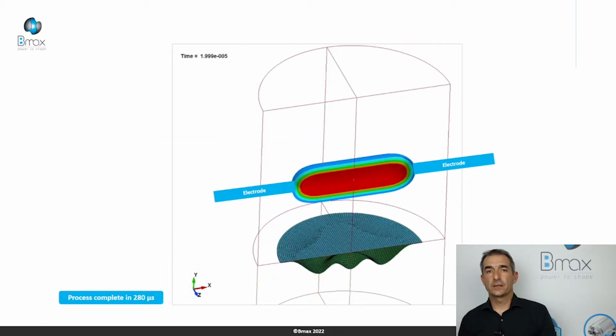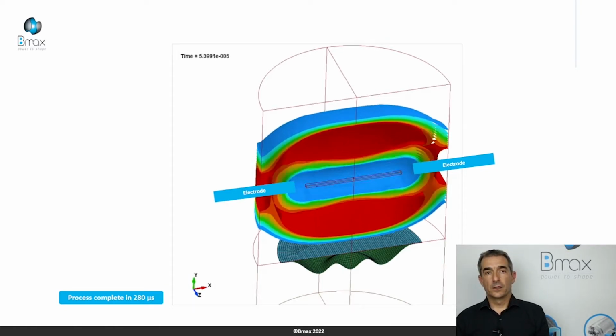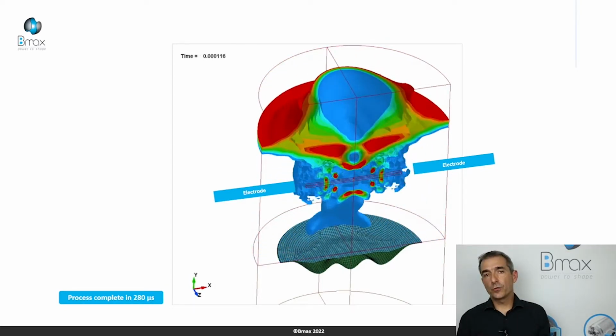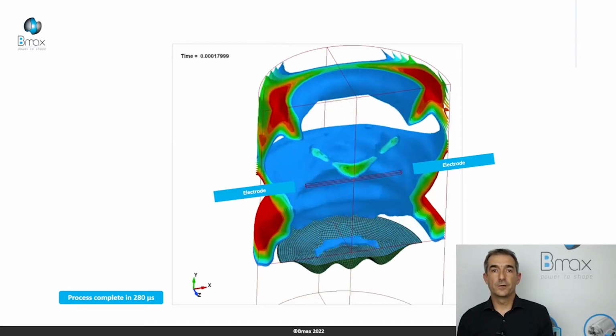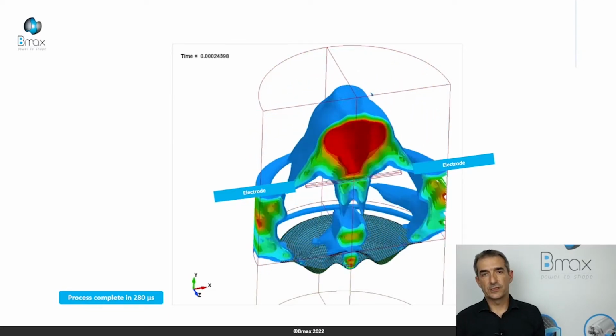Here we can see a half model of a water tank on the top with 2 electrodes. In blue, it's the blank, the deformable part. And we want to push this blank, to form this blank into the green part. It's a rigid die. We perform an energy deposition, and all the fringes, all the colors, are the pressure wave generated due to the energy deposition.